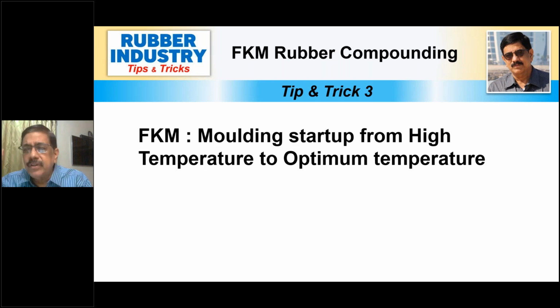Many times, these industries will maintain the temperature of the platen at 175 degrees and say that they have maintained 175 degrees. But in true reality, the FKM rubber should encounter 170 degrees. It is not the platen or press temperature that matters, but the temperature at the mold. Many people will not understand this. They will not focus on the temperature on the mold, because the mold is a moving object and they can't sense it properly.